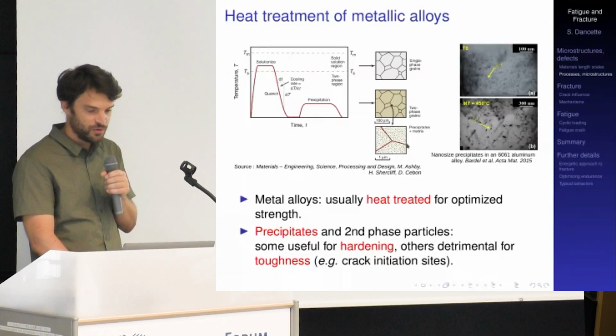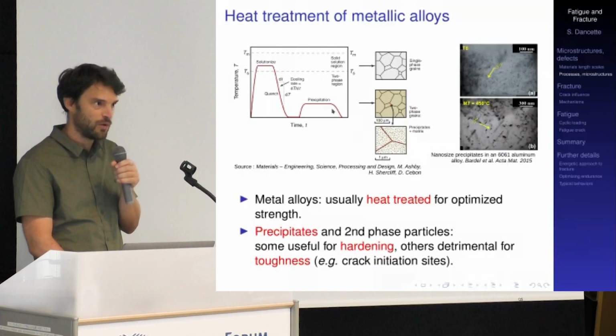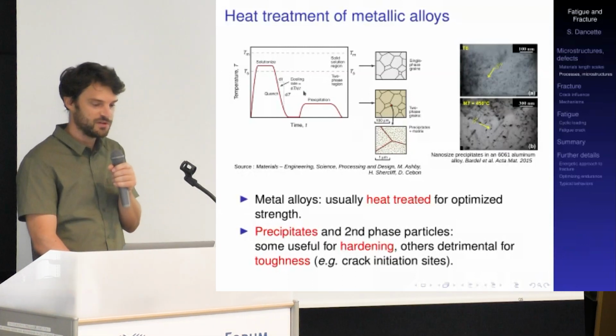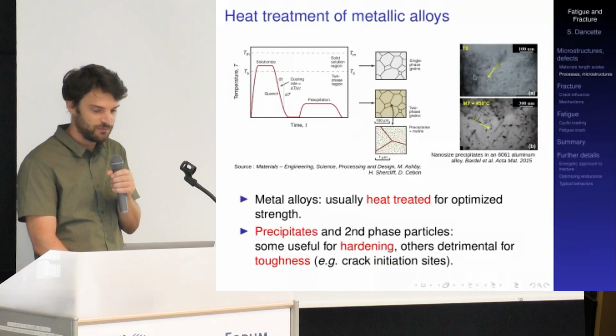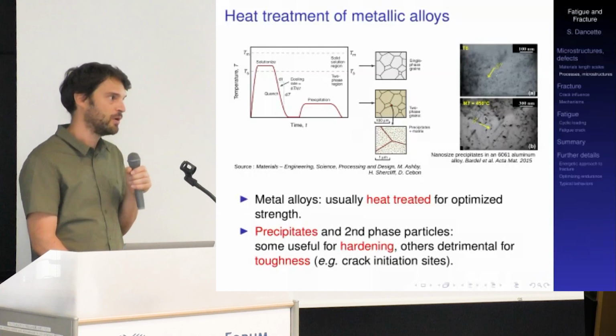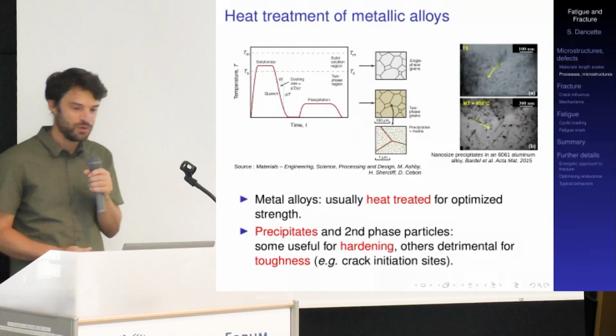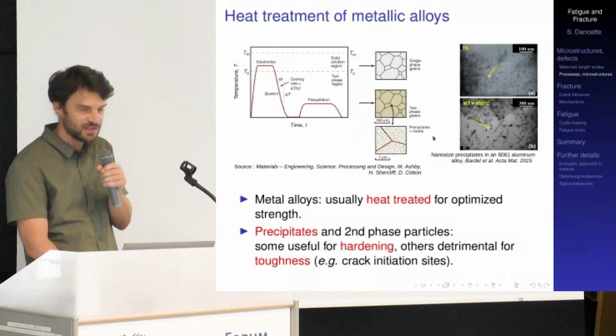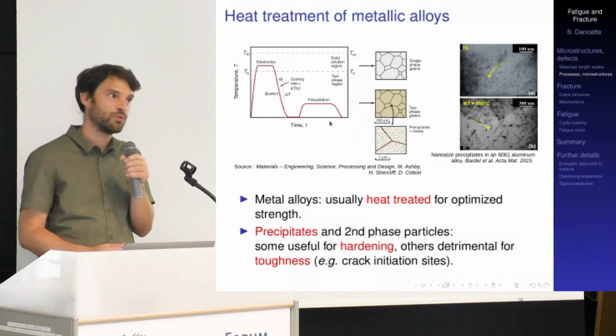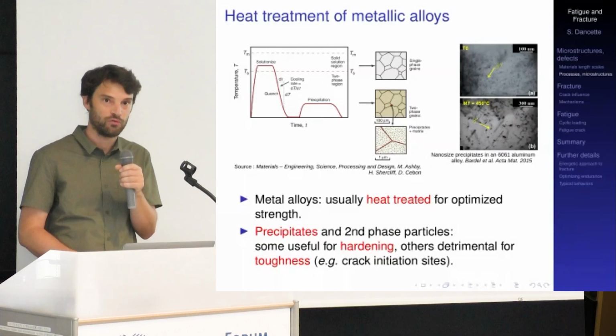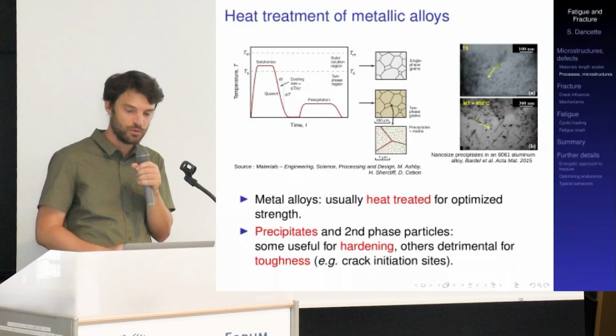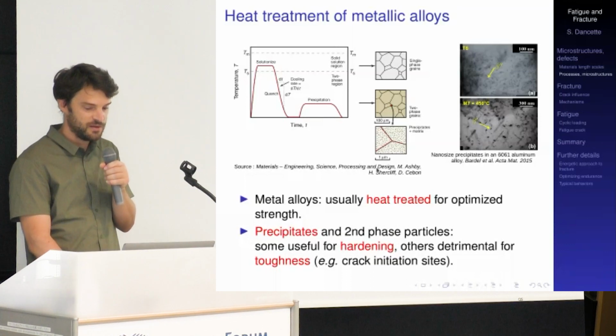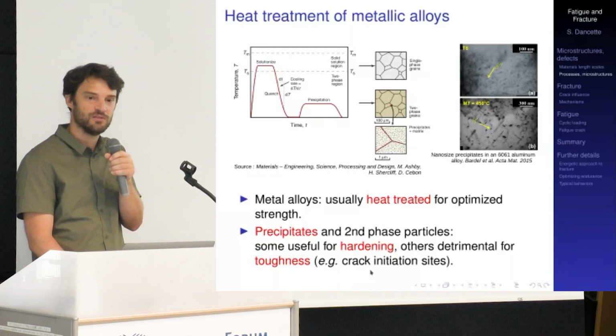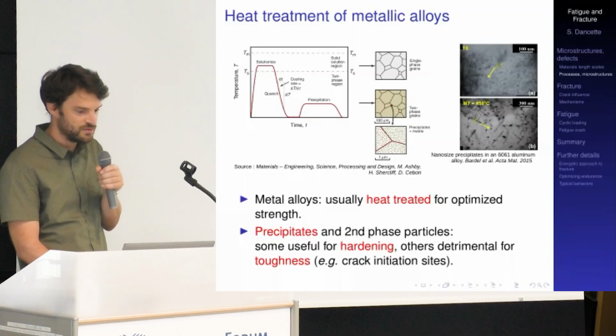And again, depending on the type of precipitation heat treatment, depending on how well you control the temperature or the time during this precipitation heat treatment, you may have several types of second phase particles here, precipitates, from coherent nanometric precipitates to coarser semi-coherent or incoherent precipitates. And again, depending on the nature of these precipitates occurring inside of the grains during the treatment, this may have a very strong impact on both mechanical properties of the material, strength, yield strength, for example, but also on fracture properties. And it is not uncommon that such second phase particles constitute, as we will see later, the crack initiation sites in the microstructure of the material, in that case, of the metallic alloy.